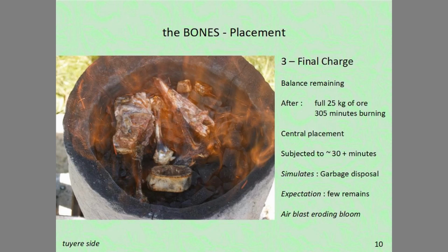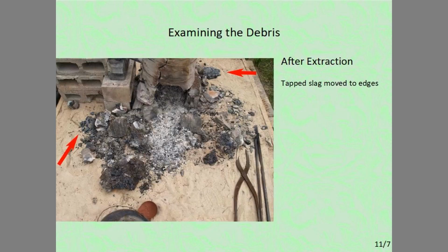Those familiar with iron smelting will notice the bright sparks seen in this photograph. This is an indication of the air blast eroding the top of the bloom, potentially the bloom sitting too high in the furnace. Careful examination of the resulting debris would be important to determining what bones may have survived.